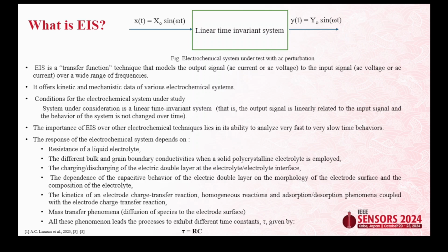For example, if I was working with electrochemical sensors, and initially I was keeping the concentration of my electrolyte as 0.01 molar KCl solution in buffer, but I was not able to get the measurement, because whatever processes were happening at my electrode surface were hampered by the resistance of the electrolyte. So we shifted to 0.1 molar. In some cases, I checked the literature, many people have taken the measurement with 0.01 molar. There is no standard case.